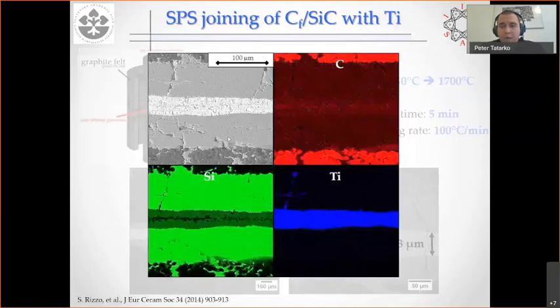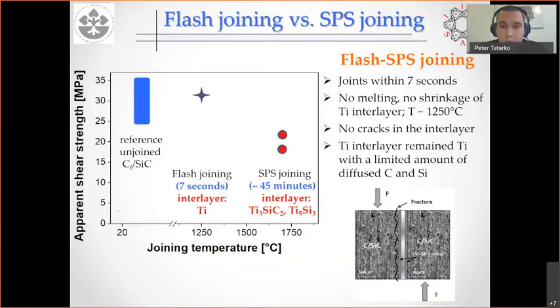But if you look at the EDX mapping, you can see again, in the middle part of the joint, it's titanium carbide. You see carbon concentrated right in the middle. Then you see silicon in here. So you see titanium silicon, so it's titanium silicide. So as I showed before, it's not pure titanium as it was in the case of the flash joining process. So here is one summary, and you see here, this is a reference unjoined sample. If you remember well, I said during my presentation that the values are between 25 and 35. This is the reference from the supplier.